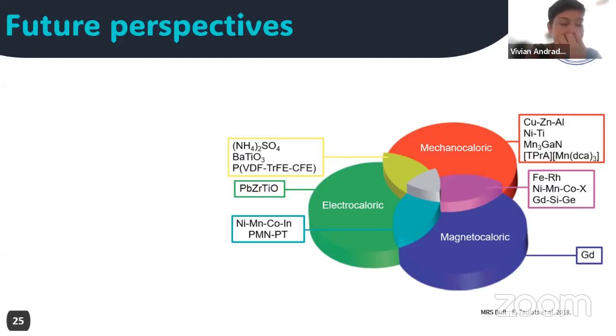Yeah, there's a lot of studies on how to obtain this phase without too much thermal treatment. For instance, one work from Bruno, a PhD student from Mario, observed that for iron 2 manganese silicon, if you don't quench after the annealing, it will crystallize in the cubic structure, which is the one presenting the Martensitic transition.